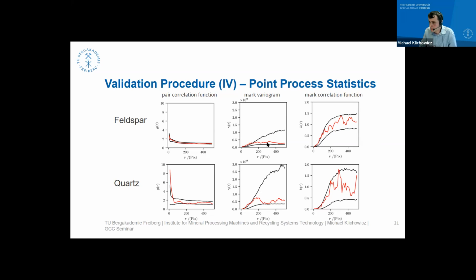I know it's a little bit complex if you're not used to point process statistics, but what we see here is that our gamma and our kr, for example, are small for small values, and that indicates that grains which are close together are of similar size and are very small. That indicates the natural fact that grains which are close together have to be small since they cannot overlap.